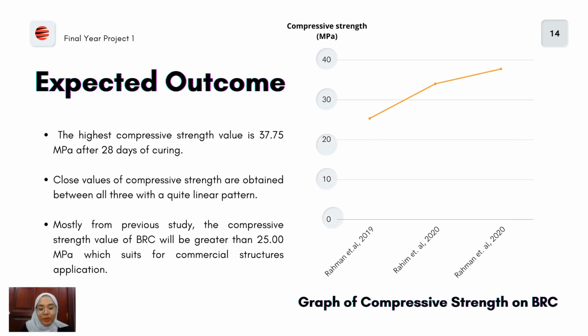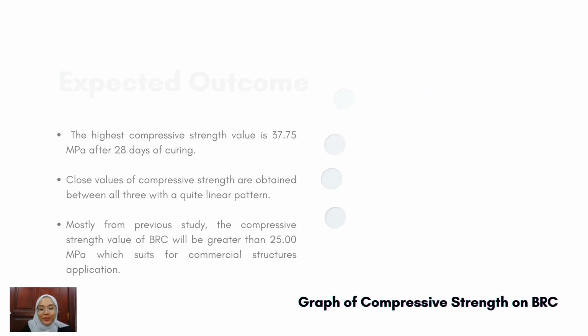The second expected outcome is a graph of compressive strength of BRC. As you can see, I've differentiated between 3 different authors, of which Rahman has shown the highest value of compressive strength for 28 days. Apart from that, it shows close values of compressive strength between all 3 with a quite linear pattern. Mostly, from previous studies, the compressive strength value of BRC will be greater than 25 MPa, which suits commercial structure applications.